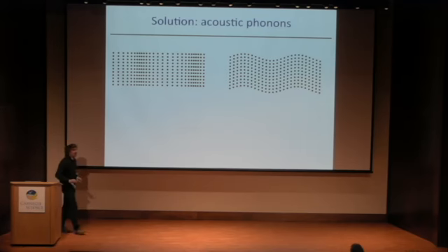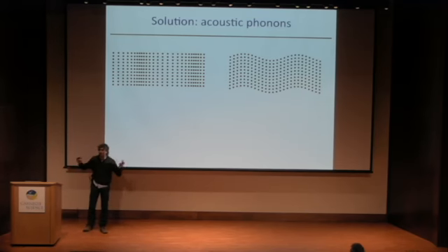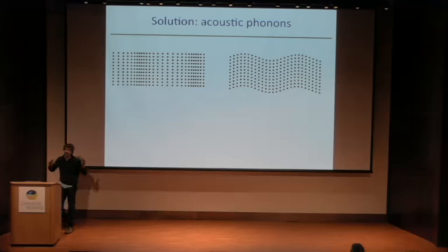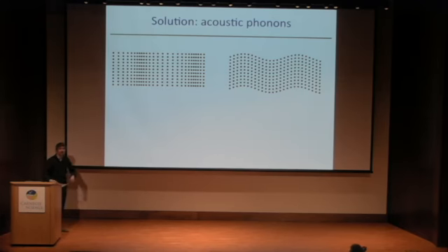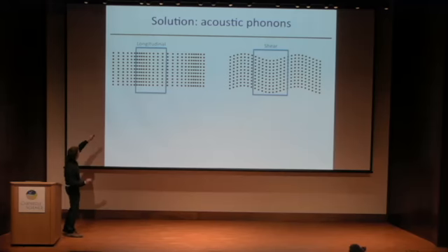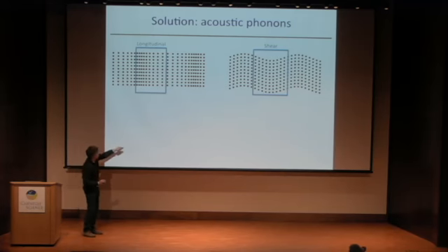And the idea is to take this non-periodic perturbation and make it at least quasi-periodic. So instead of having a macroscopic strain gradient, modulate it in a sinusoid. And so you create essentially an elastic wave, an acoustic phonon. In this case, you can see that if you take a snapshot, you recognize a longitudinal strain gradient here and a shear strain gradient here.